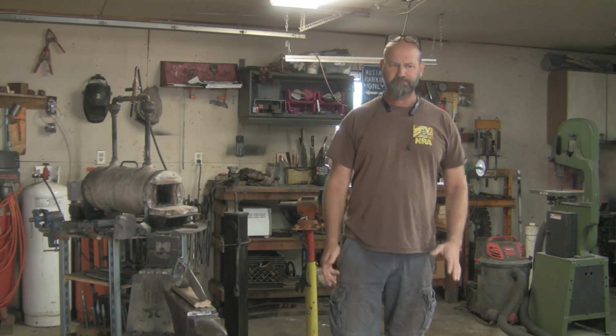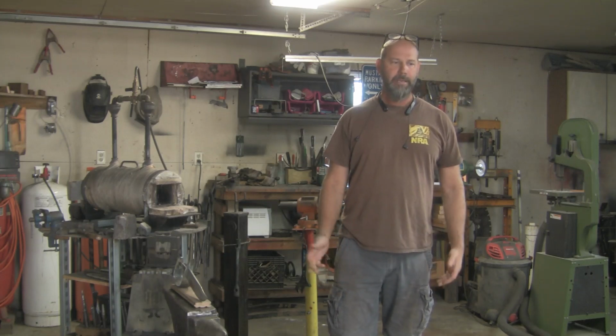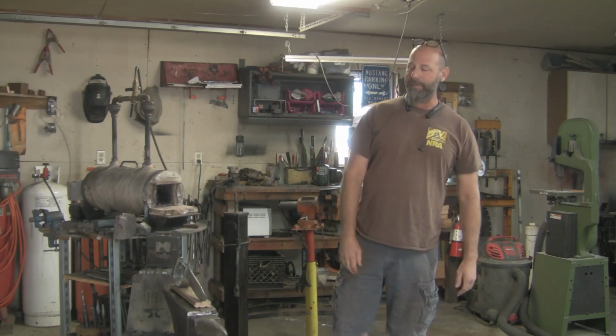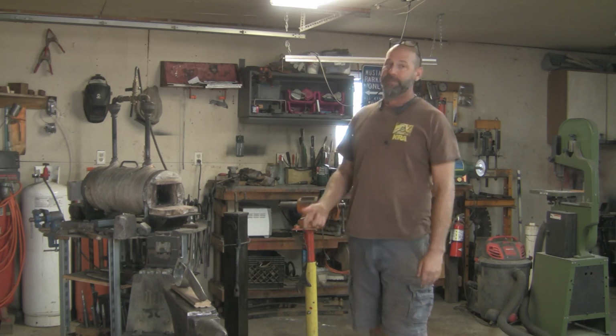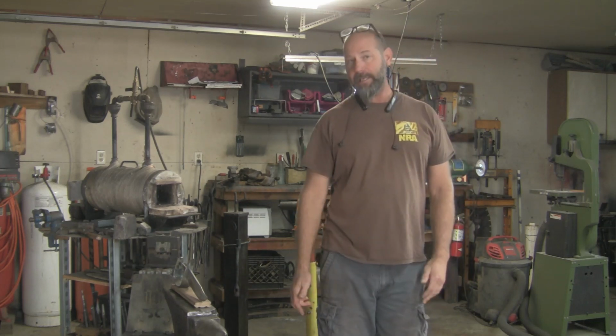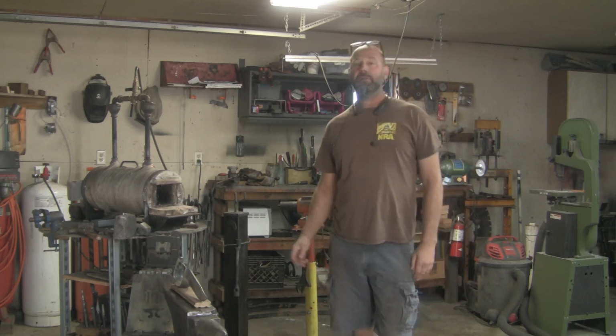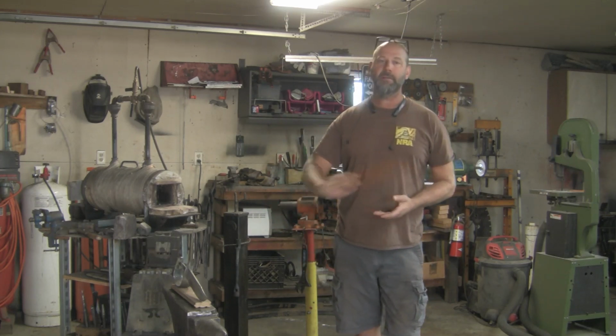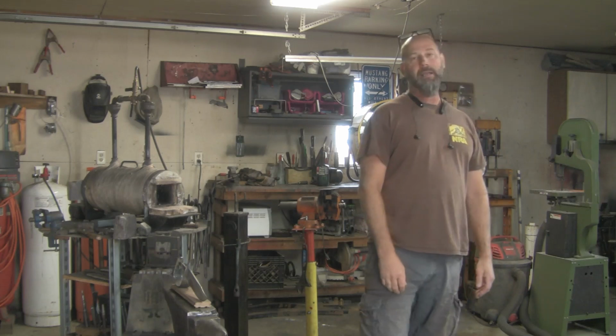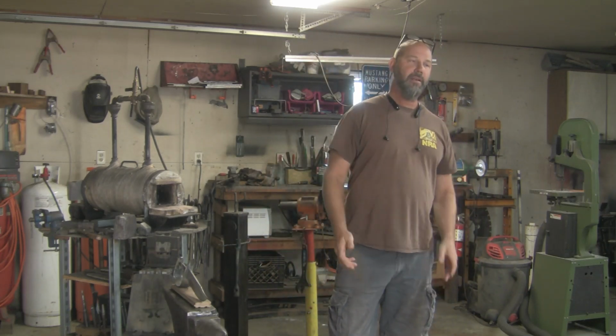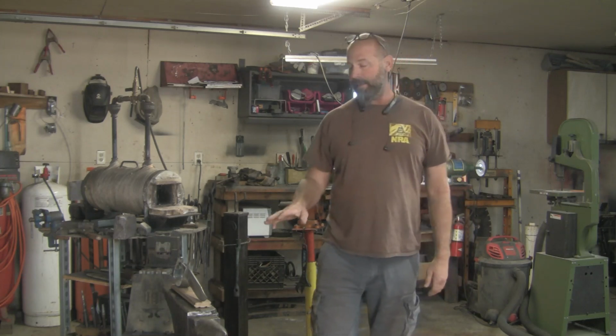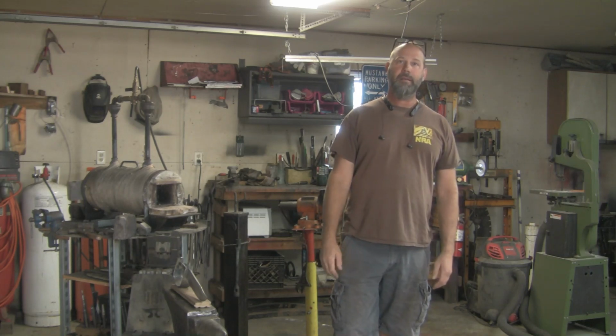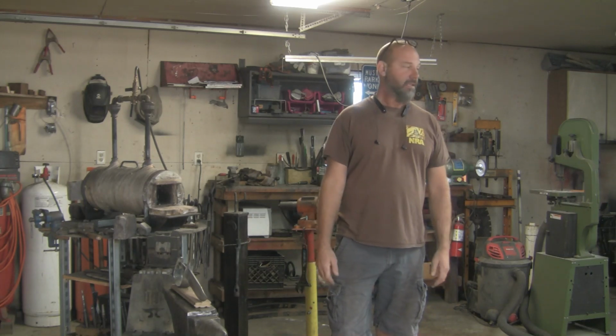And it just has to be one of those knives that you'll have to sharpen more frequently. But as far as toughness, this thing's actually pretty daggone tough. I did do a tip test on it. I jabbed the tip in a log, threw the blade over, and the tip slightly bent a little bit. It did not break off. It did not come back into shape. It did kind of bend slightly. So after reforming that, I continued with more testing.